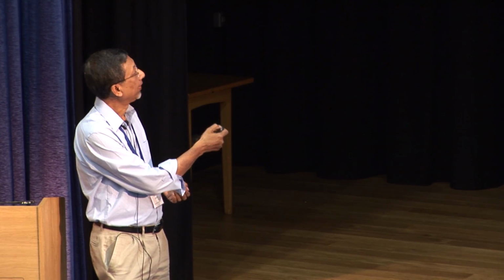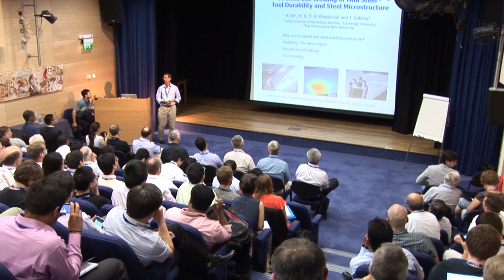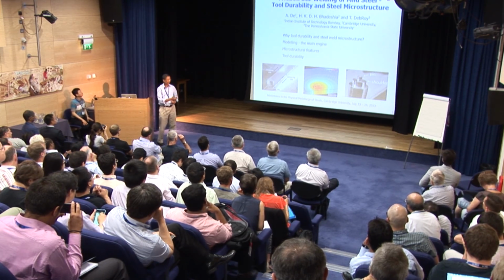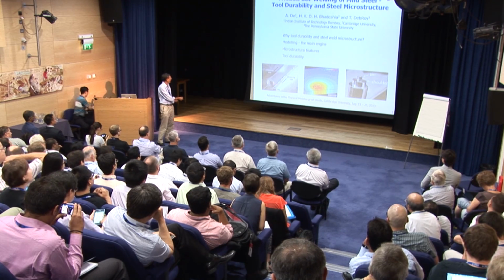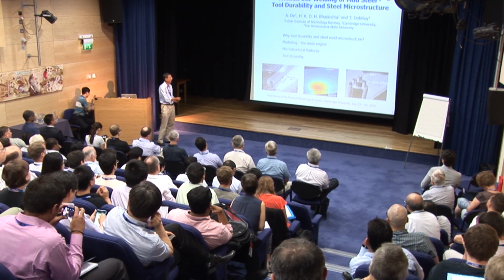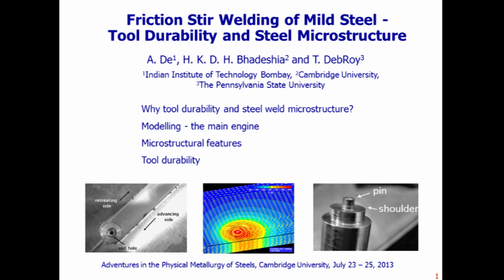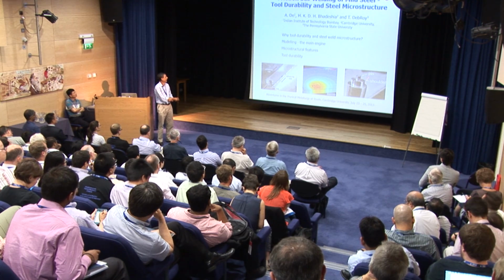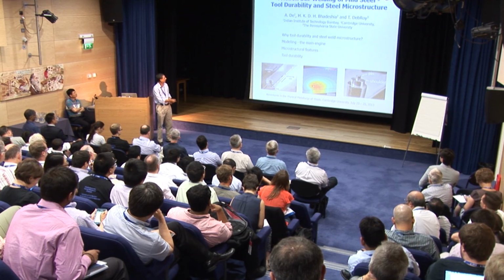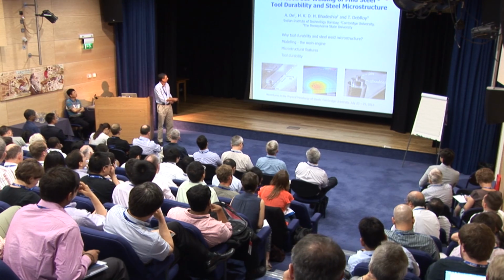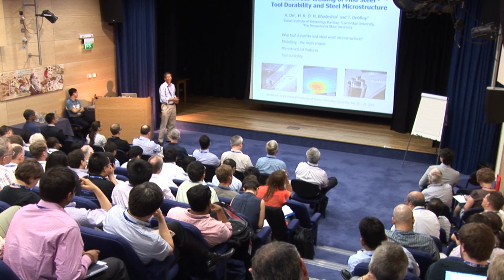Friction stir welding is not commercially used for steels. It's a very nice process for joining of soft alloys like aluminum alloys. And the problem is with the tools for welding of hard alloys, the tools wear out or the tools fail in extreme cases, and the cost of the tools remain high. Also, the problem is added by the high temperature and very rapid heating, cooling, and stresses on the tool.